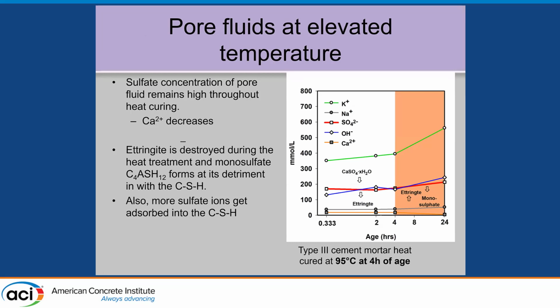However, if you cure at high temperatures, such as at 95 degrees C, the same cement, then what happens is it looks the same up to about 4 hours when the heat curing was applied. And then what you see is that the sulfate doesn't disappear. It remains constant or slightly enlarged. And because the sulfate's up, the hydroxyl doesn't come up because they have to balance the negative charges. And so where is that sulfate going? The ettringite is disappearing. Any existing ettringite gets destroyed at these temperatures, and some monosulfate forms, precipitates out. But a lot of the sulfate gets absorbed into the CSH itself, and that becomes part of the story.